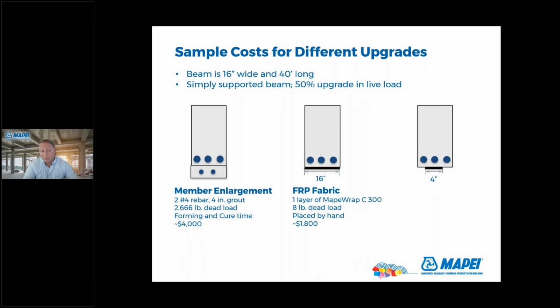Now, if you use the fabric, one layer of our lightweight carbon fiber, that's going to add about 8 pounds of dead load. Place that by hand. Materials and labor is going to come out somewhere around $1,800. Now, if you did the plate, one strip of a 4-inch plate, same amount of dead load, placed by hand, that's going to come out around $1,400. So just so there's different ways to skin the cat, and each project is different, but in general terms, this is what the cost difference looks like for strengthening beams.